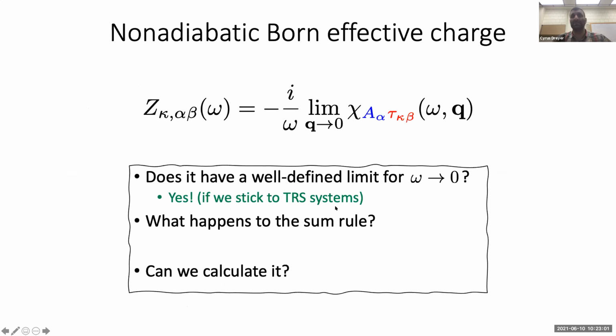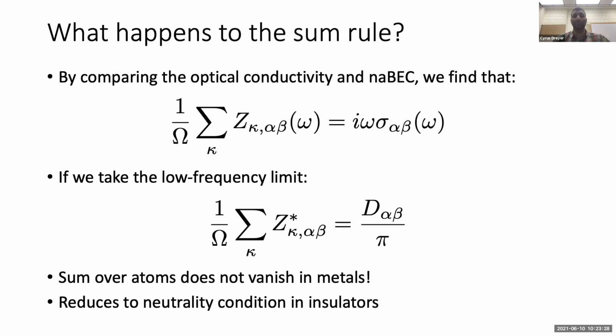Now the next question we ask is what happens to that sum rule? As I said at the beginning, when we have a Born effective charge in an insulator and we do a sublattice sum over kappa, every element of the Born effective charge tensor has to vanish. Is this still the case in a metal in terms of this non-adiabatic Born effective charge? And the answer is no. We can see this again by comparison between the Born effective charge and the optical conductivity. Before I was just comparing them at a heuristic level, but we can actually get a direct proportionality between not just the Born effective charge, but the sublattice sum of the Born effective charge and the optical conductivity.